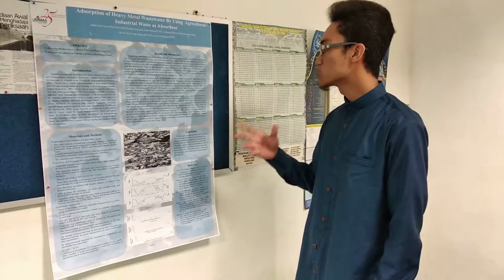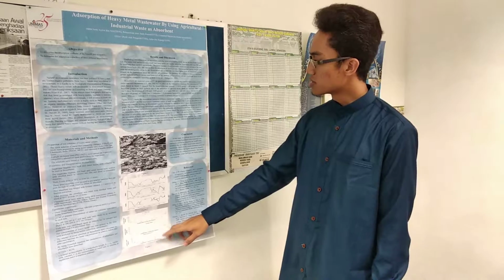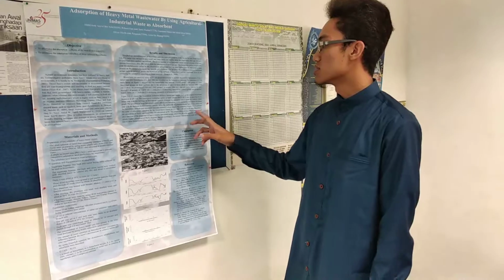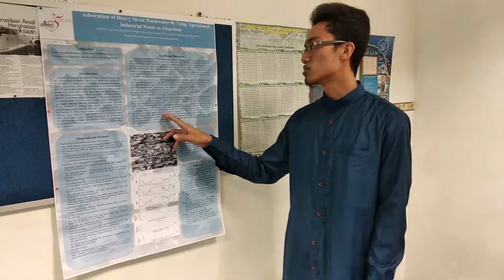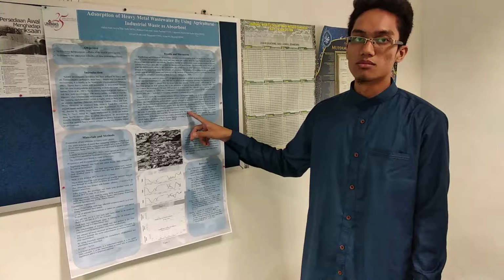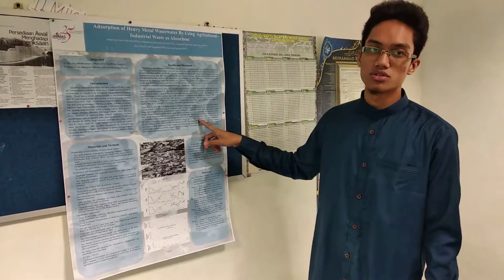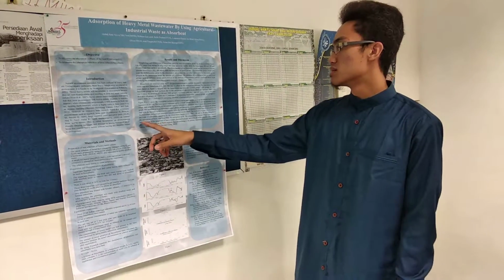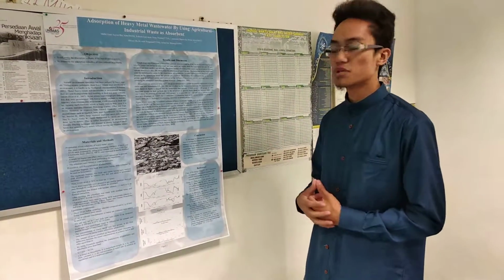The isotherms in figure 3, A, B and C, indicate that the order of absorption capacity for the tested heavy metals is CL the most, followed by RH, and then SB, which is sugarcane. In all of these bioabsorbents, the absorption of nickel was lower than the absorption of Pb.